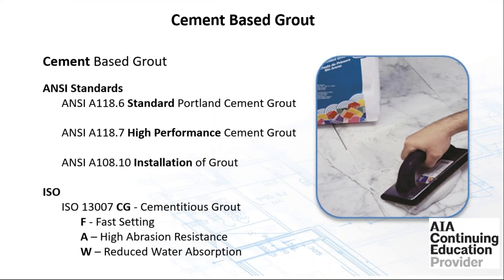So the ANSI standards for the cement-based grout, A118.6 is the standard Portland cement. A118.7 is your high-performance calcium aluminate, high-hydrated cement. And A108.10 is the installation of the grout, that process. Now, ISO standards. ANSI are very, very important. However, when you get into the ISO standards, that really breaks down the product itself. It gets very specific, so it lays out what actually am I going to be specifying, giving you the additional categories being an improved, a fast setting, high abrasion resistance. Again, I can't say enough about the ISO standards as far as getting the product specified onto the job site. Very, very critical in a specification.